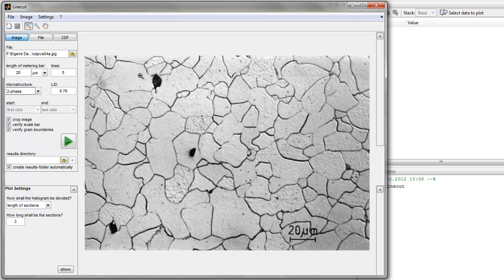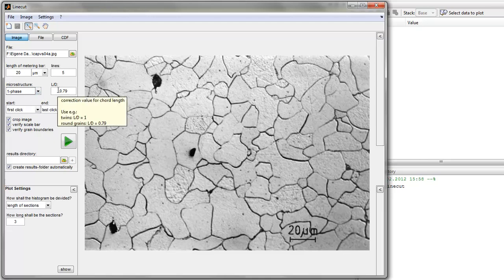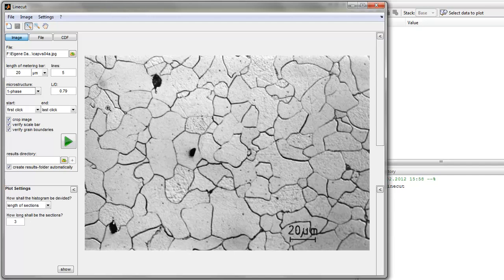So you can click here and here to mark this grain. Then for the next grain you have to click here and here again. So this is one phase. L/D is a correction value for the chord length. If you want to analyze twins you have to choose one, or as here for round grains it is 0.79.